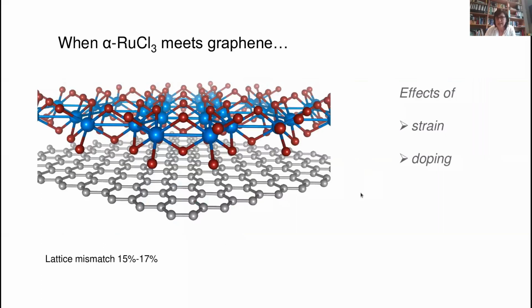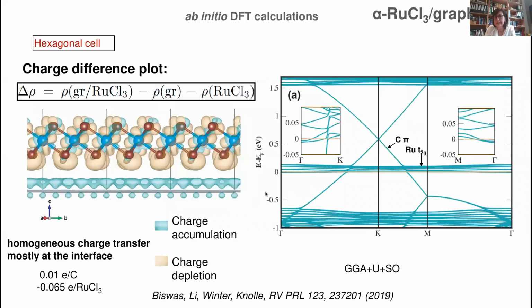Now one has to say that there is a big lattice mismatch between these two systems, and one expects effects of strain and doping between the two. So what we did is density functional theory calculations where we create these heterostructures and look at what happens to the electronic structure.